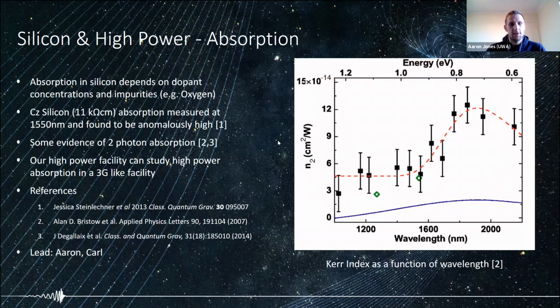Absorption in silicon. Absorption in silicon should depend just on the dopant concentration and the impurities, such as oxygen. There's been quite a bit of work on this, so there's a few different ways you can make silicon. One method is the Czochralski method, and a sample of Czochralski method silicon was found to have anomalously high absorption. There's also been some evidence of two-photon absorption, and you can see this on the plot on the right-hand side. We've got the wavelength across the bottom, and then we've got the Kerr index on the left-hand side. This isn't my work. This is from this reference, Alan Bristow in 2007. And you can see that around about 2 micron, you've got this anomalously high value. It's not actually anomalous. It's explained by two-photon absorption. So with our high optical power in our ITM, again, we can explore this and see if this is going to be an issue for us.